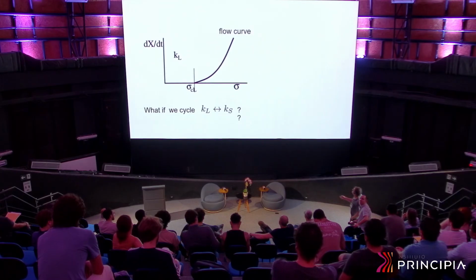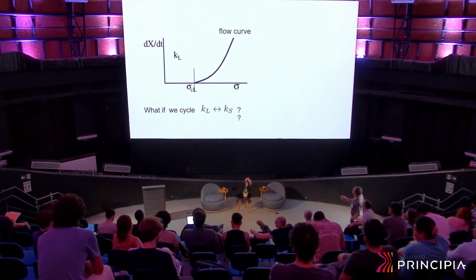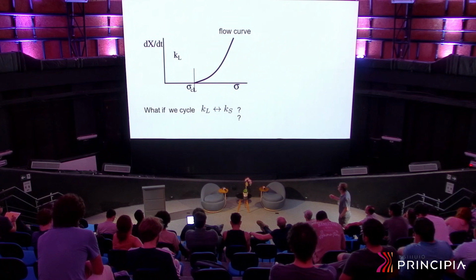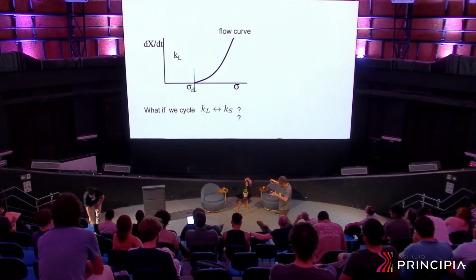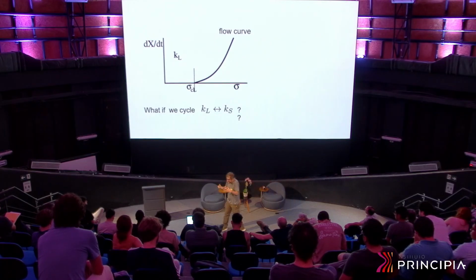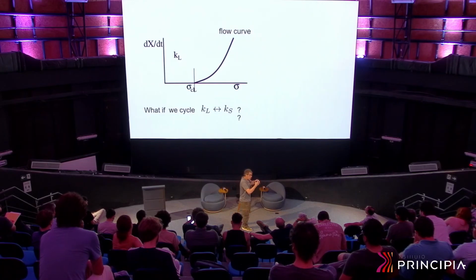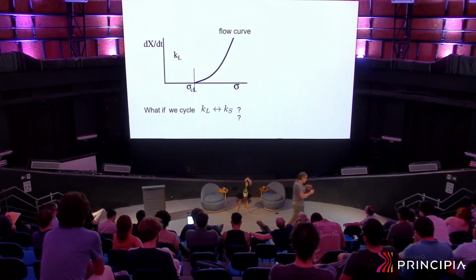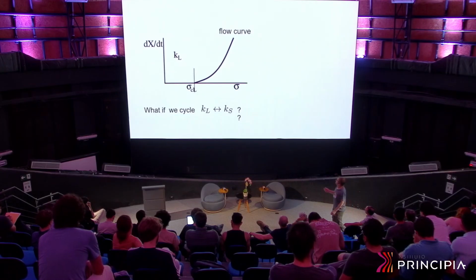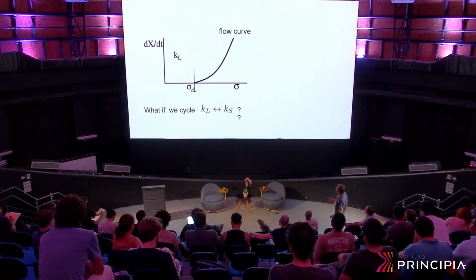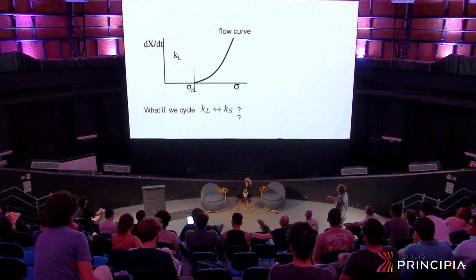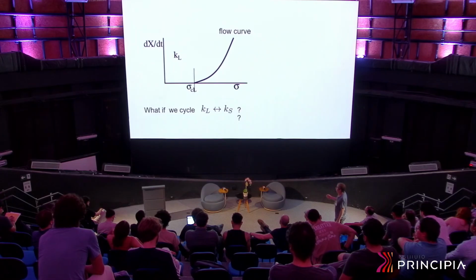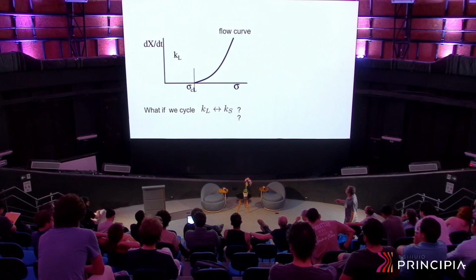The point I want to stress is that if I consider the system for a given value of this constant k, which is essentially the overall value of this strain kernel, if I increase k, it means that I make the system more rigid. If I decrease k, I make the whole system softer. As I said before, probably what we could do to make a model of the soil creep behavior is change this value of k from a large value kL to a small value kS and see what happens.